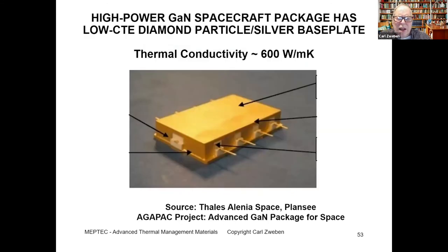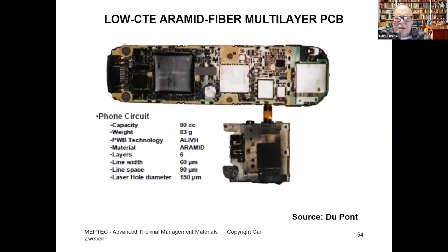This is an experimental package consisting of a base plate made of diamond particle reinforced silver, which again has a high thermal conductivity combined with a low coefficient of expansion and a lower density than silver or copper. Thermal conductivity here is 600 watts per meter Kelvin. And again, that's isotropic. This is an example of an aramid fiber reinforced polymer printed circuit board, a multi-layer printed circuit board. And again, this has a low CTE, and as far as I know, it is a production application.